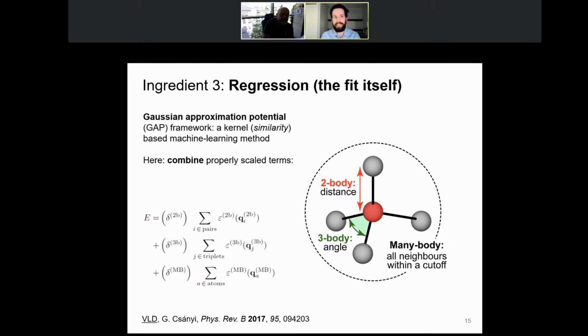Great question. So in principle, you would hope that the larger you make your cutoff, the better everything gets. And in fact, one of the primary limitations of this approach is the fact that it is fitted to short-range descriptors. It turns out in practice, there's often a limit at about 5 to 6 angstroms from what I've seen. There are ways of including longer range interactions. There's some that colleagues of mine are working on. We are. There is work by a group.